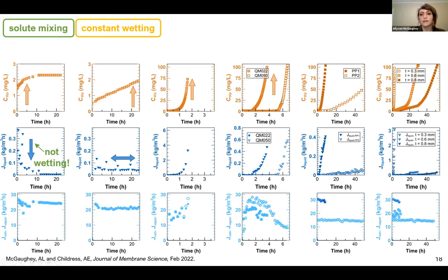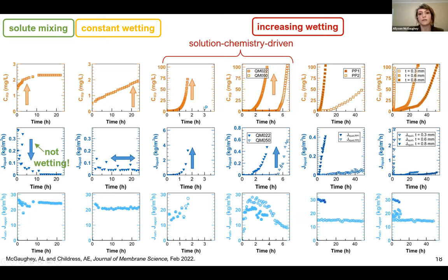We saw increasing CDP with increasing liquid flux, and we call that increasing wetting mode. We saw that that was associated with solution chemistry effects for surfactant, as well as scaling-induced wetting, independent of membrane pore size. And finally, we saw increasing CDP at increasing liquid flux under baseline conditions for certain membrane materials. We're hypothesizing that this may be due to high pore interconnectivity, which is a subject of ongoing study in